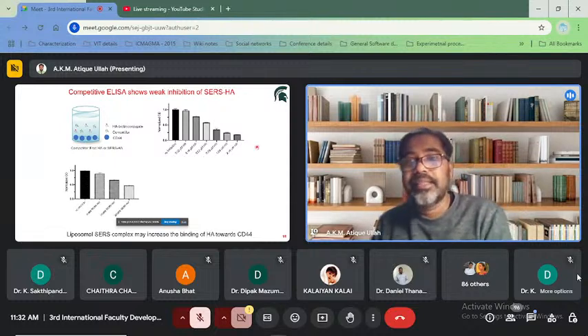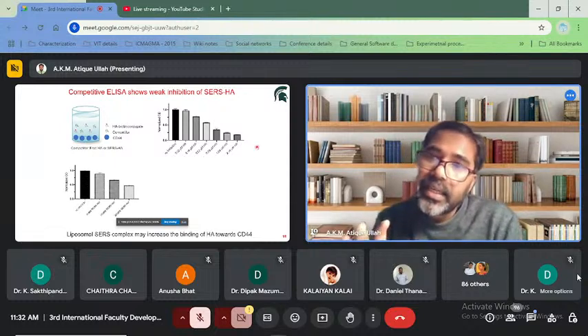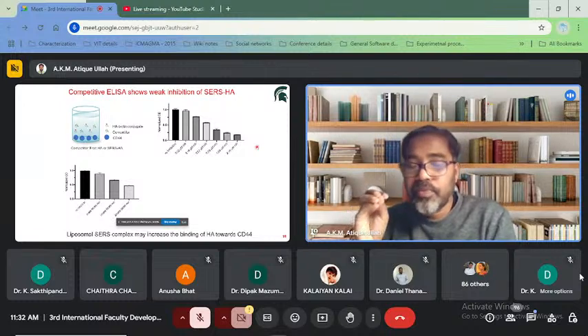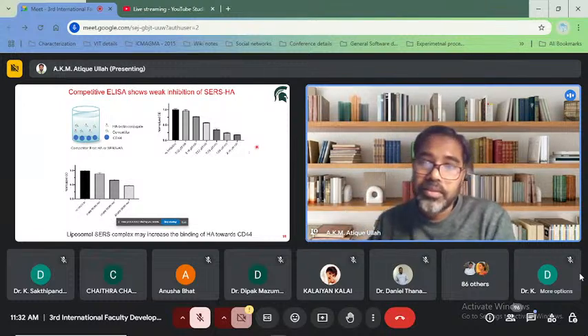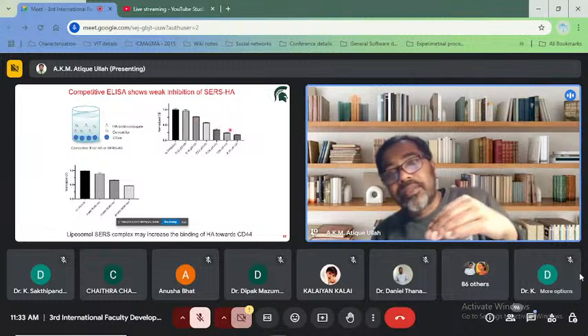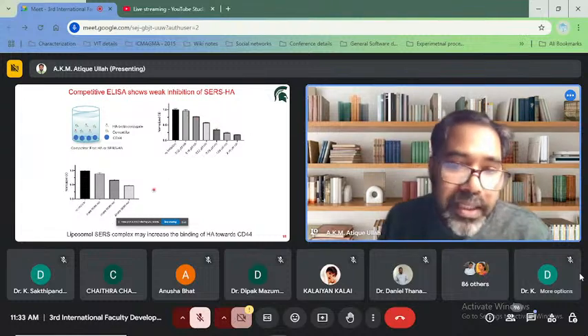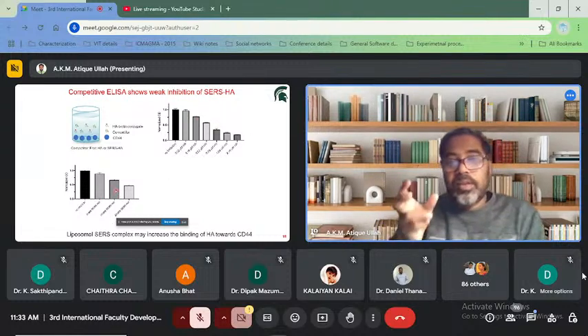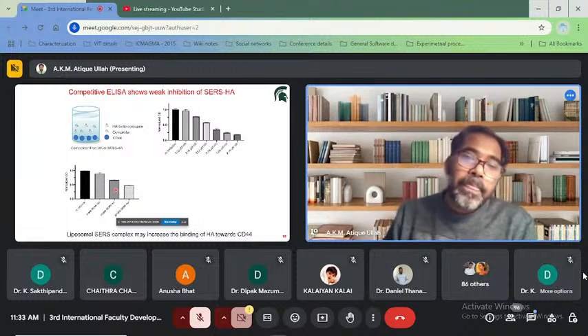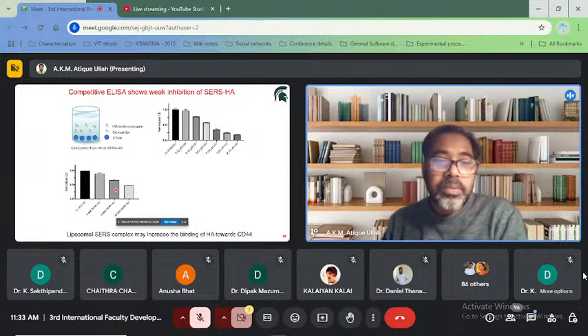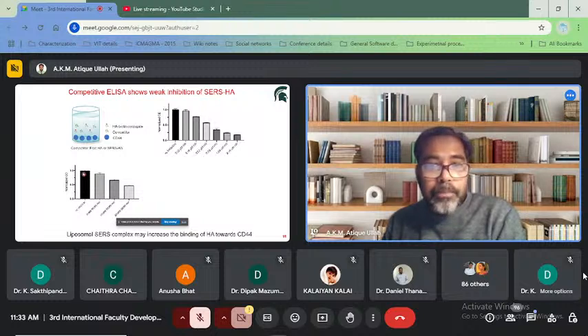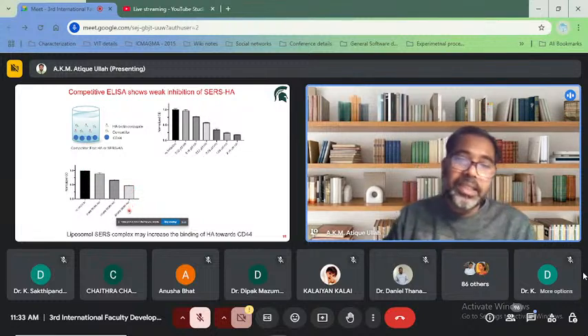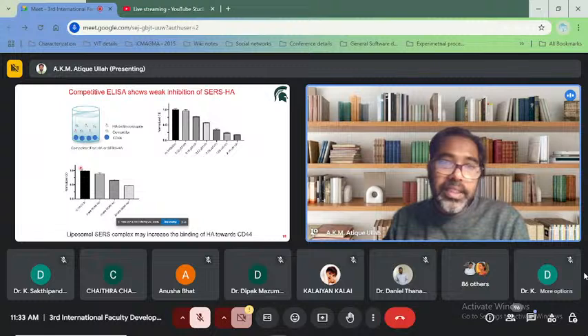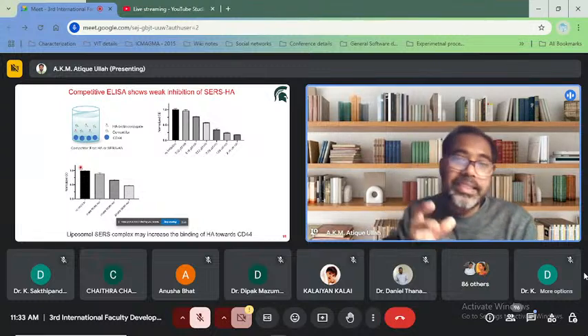This is the free HA, without functionalization of the HA onto the gold nanoparticles. You can see the HA can selectively bind to the CD44 protein. Then we worked with the HA-functionalized gold nanoparticles. You can also see that with the increase of the concentration of the HA SERS nanoparticles, the binding affinity is increased.